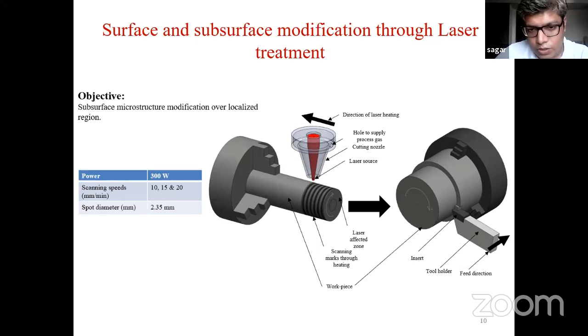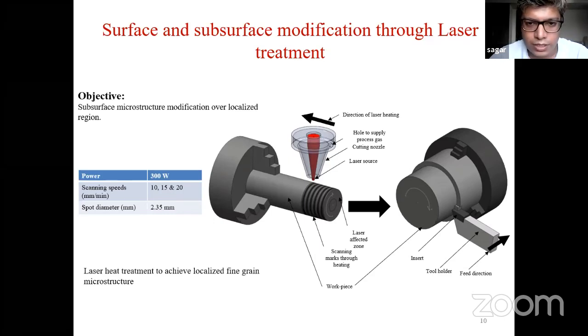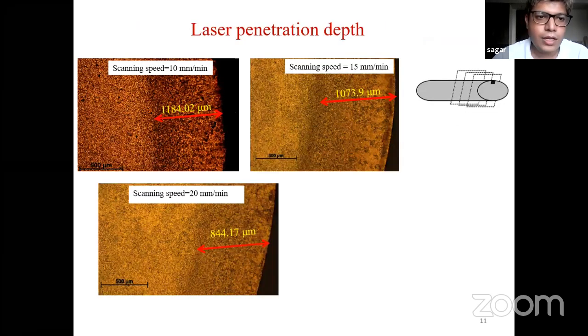So that's why you could see very fine grain structure forming at localized level. Okay, let's move ahead and see the results of this. Here you could see with 3 different scanning speeds we can achieve different depths of penetration. This is the laser treated sample. If you take the section of it, that's how you could see the penetration.